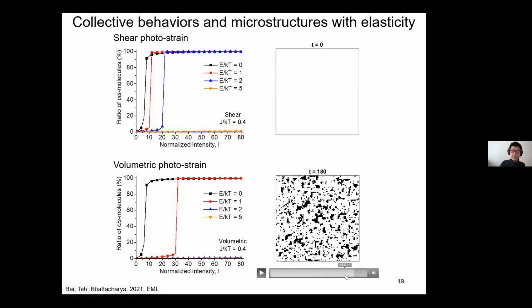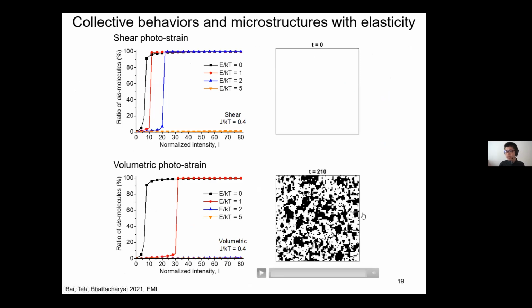Now, you can see I don't really have a very nicely looking microstructure. In fact, I don't even know what the shape of that is, right? It seems a mess in this case. And also you look at the detail of the curve. This color represents some elastic modulus. So having the same elastic modulus, let's look at the blue curve. At this level of light intensity, my whole system already flipped. So I finished the photoreaction. However, at the same level of light intensity, I just cannot flip this volumetric system. It can never flip within this range. It's much, much harder to actuate this material than this material. That's what I want to say.